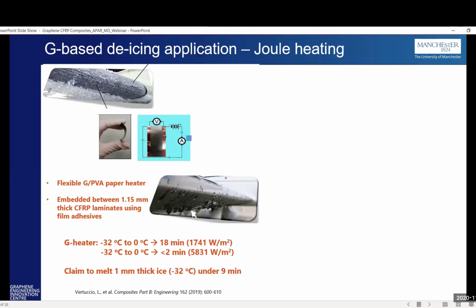And because of the resistance increase, there was heat increase with the application of current, and they can use the heat directly as a heater itself. So this flexible heater was then converted into a carbon fiber laminate, which was then molded into this wing sort of structure. And they claimed that by heating it at a high power density, this heater is very efficient, such that it heated up from minus 32 degrees to 0 degrees in under 2 minutes.